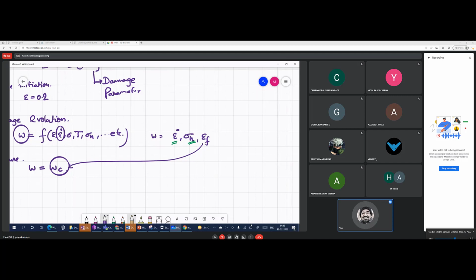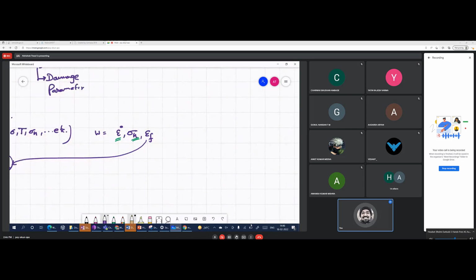Okay, so in order to simulate this thing, or in order to fix the damage evolution criteria, the real way is to conduct a lot of tensile testing. Okay, and how will you ensure that the tensile test which you are doing is at a constant constraint value? Okay, because it's a function of constraint. So from one tensile test, how will you find out at which failure strain or at which strain the damage starts to begin or the material starts to neck? Because once you neck, the constraint has changed, right? So the ideal way of doing that is to test a lot of notched tensile tests.